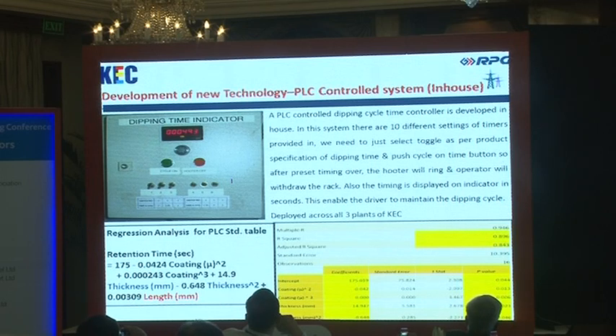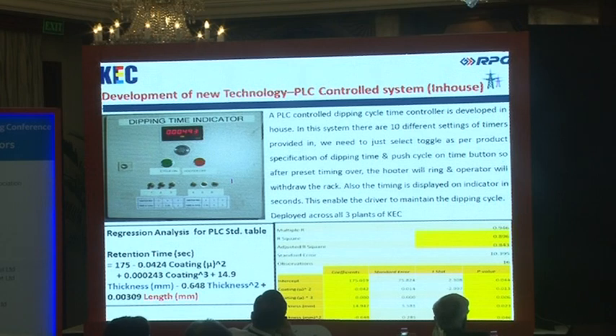That means the total surface area of a material. And we collected, I think, more than 1,000 readings for each and every type of thickness, section and length of the material. And we did the regression analysis and developed this particular formula. We validated this formula as per the coating requirement of the customers. As per that formula, when we give the input of the length and the section thickness, we get the retention time, the actual immersion time when the zinc coating process is carried out inside the bath. That is the chemical composition of that thing.